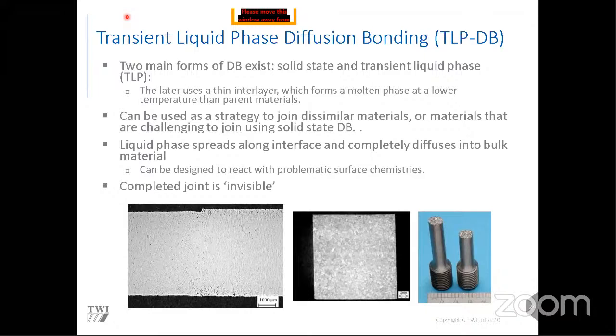What you can also do with certain material groups which are compatible is form a eutectic phase between the parent materials, and try to utilize this to get a small molten zone between the two materials. Off the top of my head, something like gold and tin forms a eutectic, or copper and aluminium.